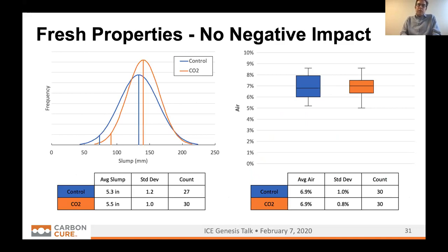You can't be sending this concrete out to a job if you're making it harder for the end user in any way. And so part of the things we have to be confident about is that the addition of CO2 is not doing anything to the fresh properties. So in this example from extended producer data, where I see I've reported inches on the bottom, an American producer is coming in with concrete, and they measure the slump, which is a measure of the workability, and they're finding that there's really no statistical difference between the slump of the concrete produced with CO2 and the slump of the concrete produced without CO2. So they're confident that the concrete, when they ship to the job, will have the right workability.